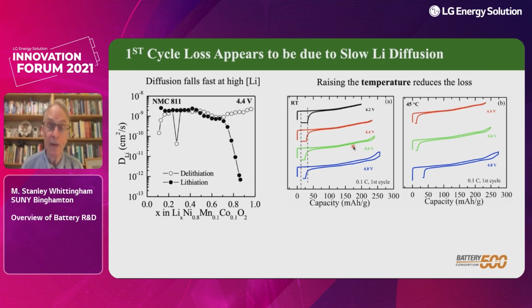So using these carbonate electrolytes, in this case, we're getting side reactions occurring at these higher voltages of 4.6 and 4.8. So this is giving us problems. And you can see here, we're not even getting as much lithium back in as when we charged at lower voltage. When we increase the temperature, you can see at 4.4 volts, we get almost all of it back in. At 4.6 volts, not quite all, but this is now because these are separating. So we got more side reactions, more impurities formed on the surface. And at 4.8 volts, we're losing a lot of capacity. So using this 811, and using the carbonate electrolytes, they are not stable at 45 degrees centigrade much above 4.4 volts.